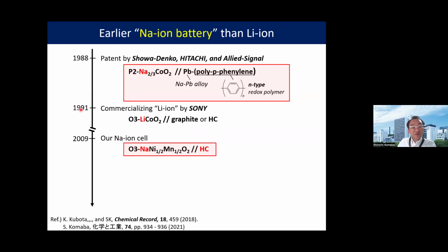And about 20 years earlier, Sony reported the first lithium ion cell based on cobalt oxide and graphite or hard carbon. It was very, very surprising that 3 years earlier, a patent was filed by Showa Denko, Hitachi, and Allied Signal Corporation reporting that P2 type sodium cobalt oxide and a mixture of metal lead and poly-p-phenylene conducting polymer show highly stable sodium ion charge-discharge properties. But we need cobalt, and also the negative electrode is so different from simple carbon material.